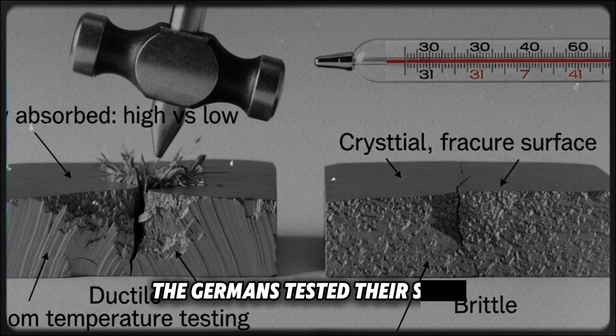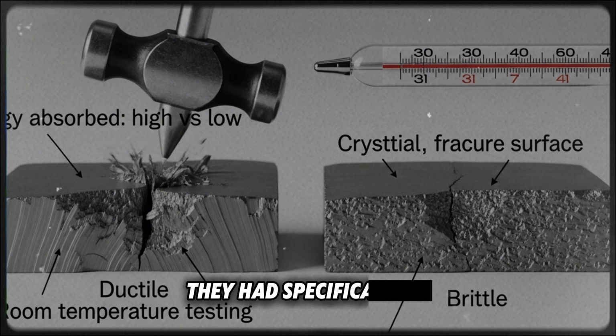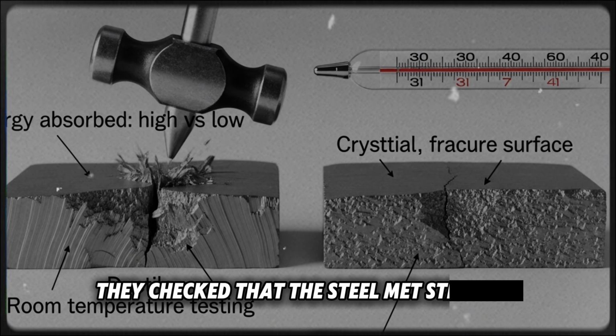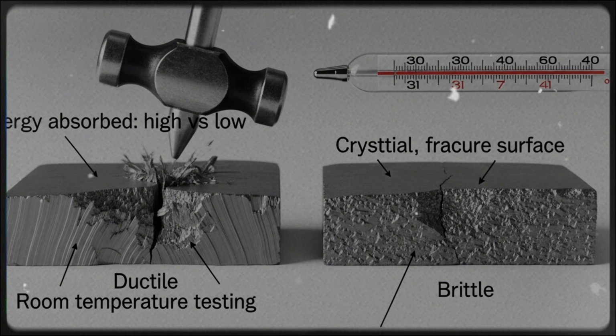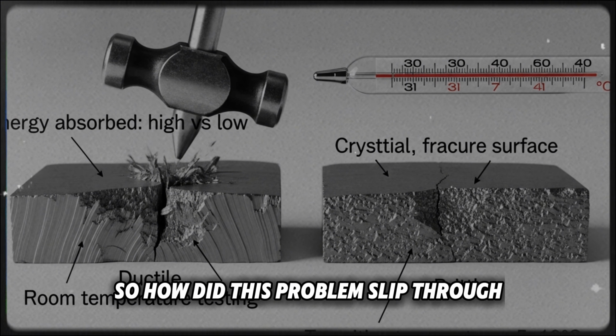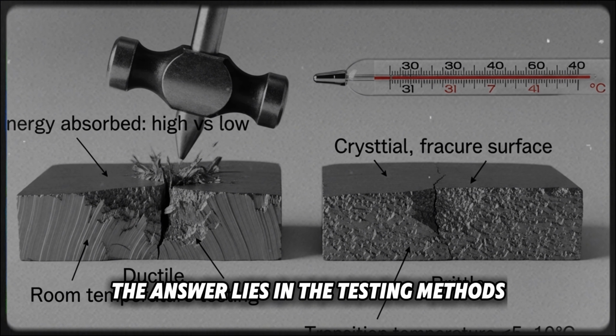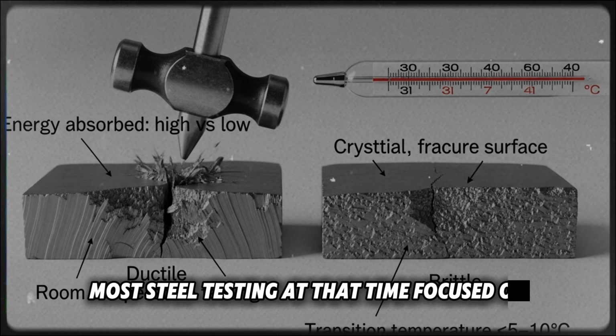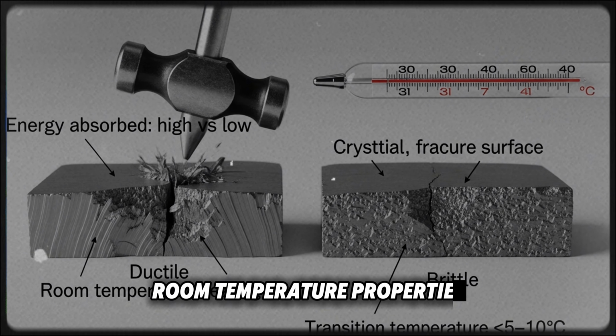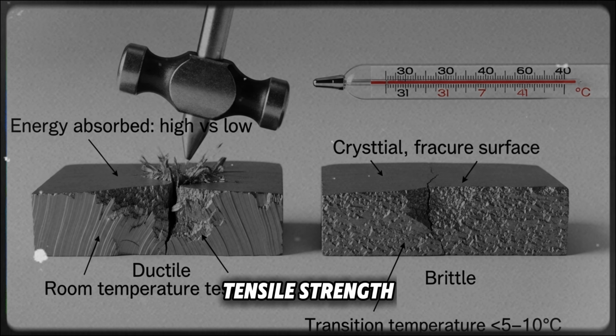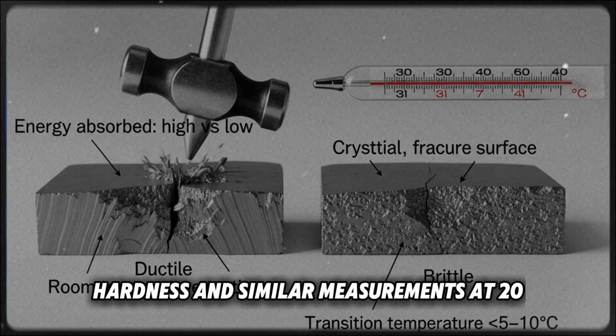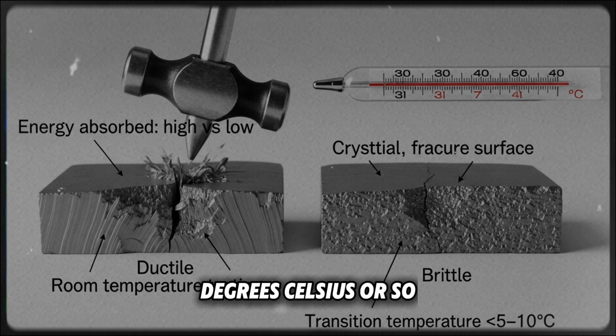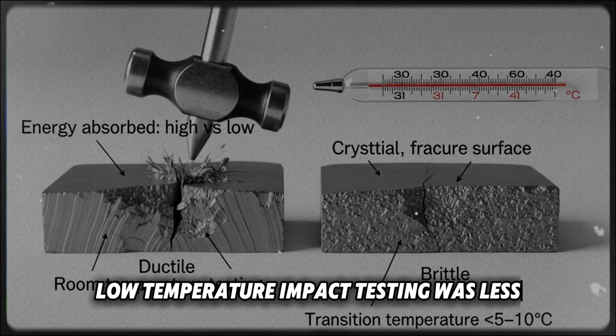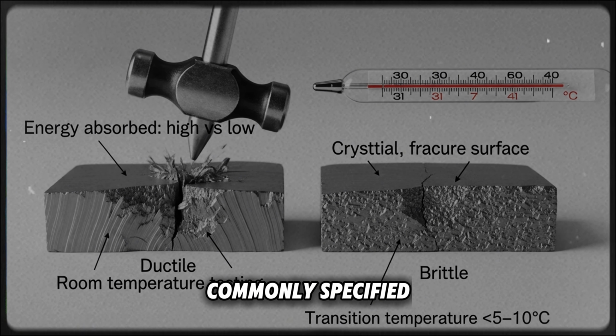The Germans tested their steel. They had specifications. They checked that the steel met strength requirements. So how did this problem slip through? The answer lies in the testing methods. Most steel testing at that time focused on room temperature properties. Tensile strength, hardness, and similar measurements at 20 degrees Celsius or so. Low-temperature impact testing was less commonly specified.